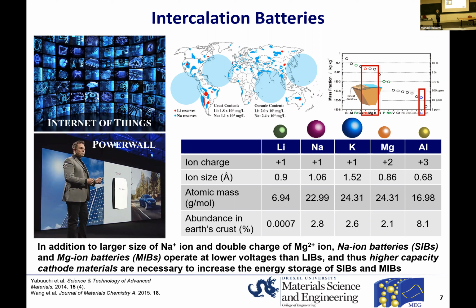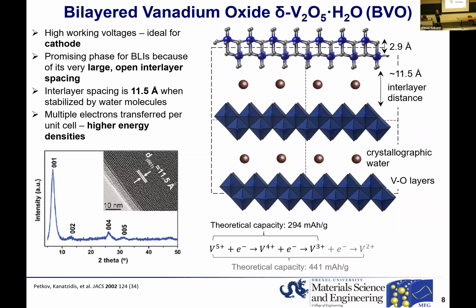So what we want to do is develop a material that would favor not only reversible lithium-ion intercalation, but also beyond lithium-ion cycling. And the material that attracted our attention for this purpose is this bilayered vanadium oxide. This is a very interesting phase because the layers in this structure are built by two vanadium rows, and that's why they're called bilayers. But more importantly, the interlayer distance in this parent phase is about 11.5 angstrom.